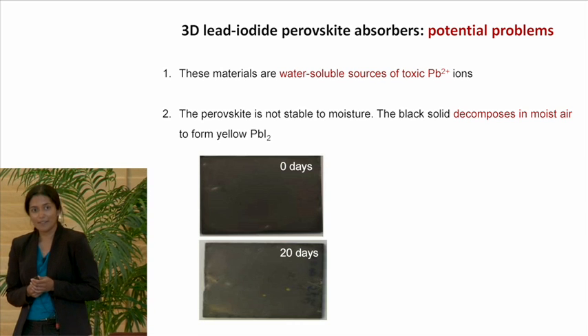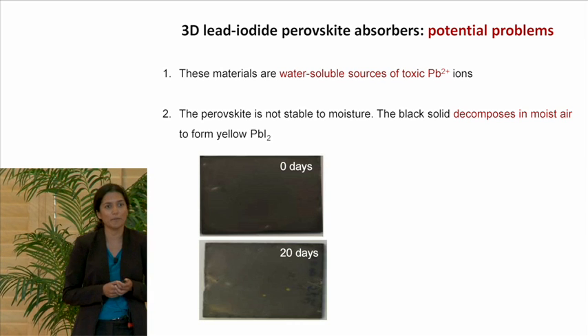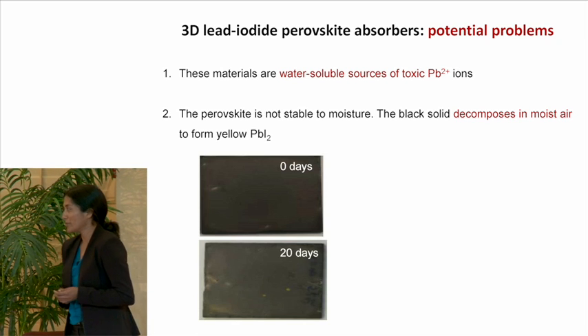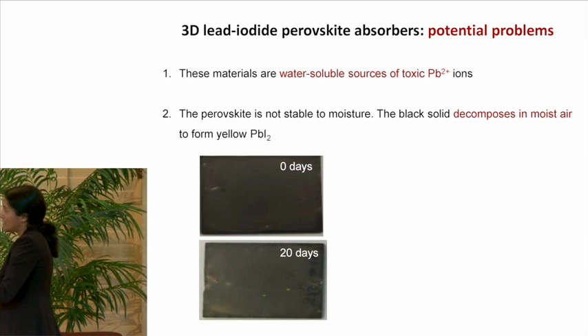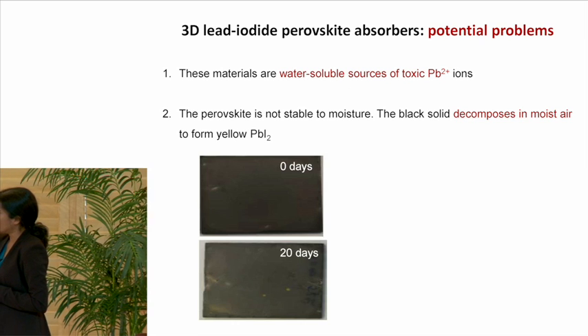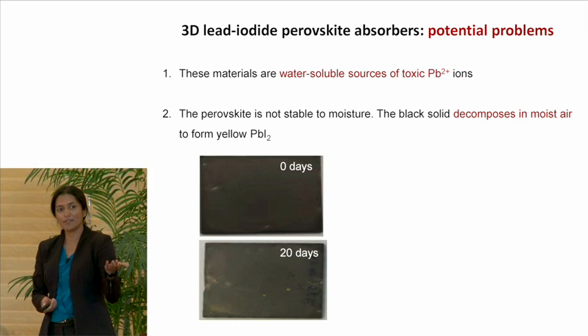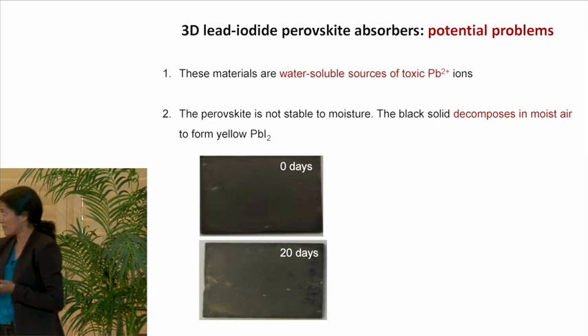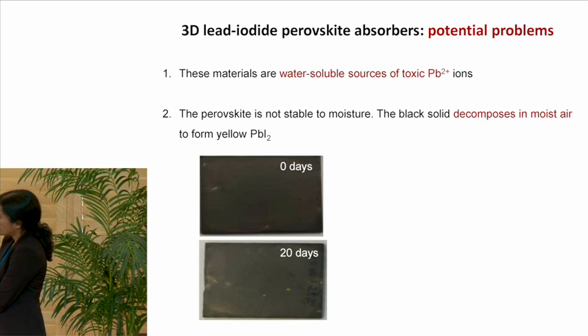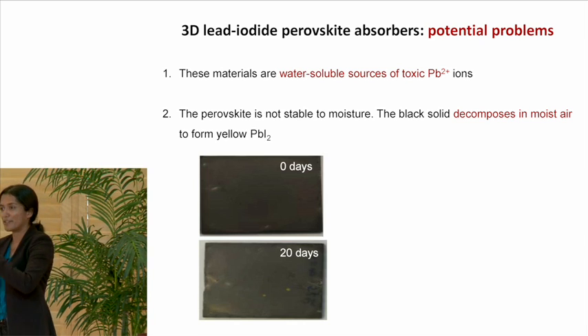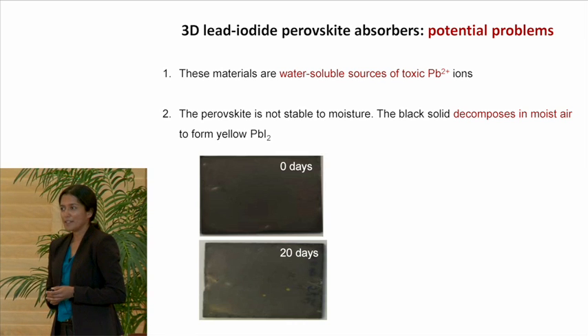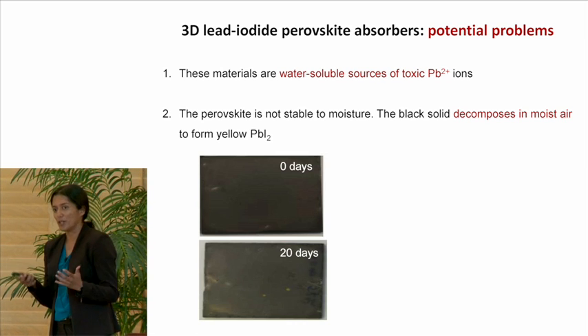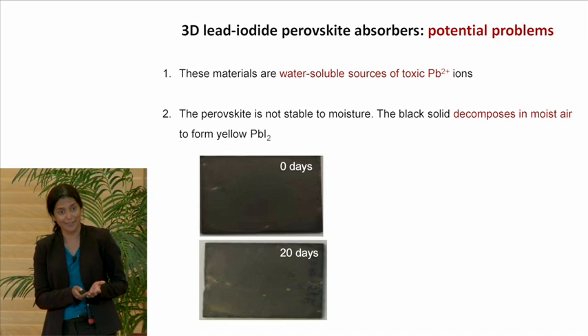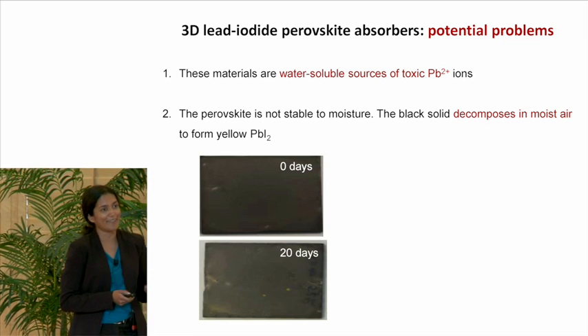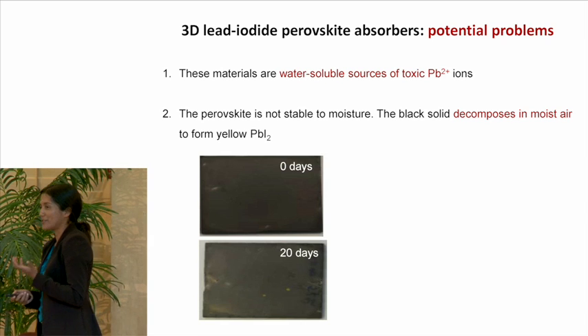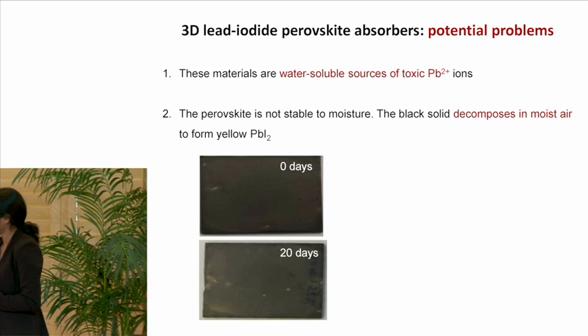Another problem that we have seen in our labs, we've seen this firsthand, is that these materials are not stable to moisture. So we can form nice uniform black films of this material, and here's a nice annealed film of the 3D perovskite, and if you just let it sit on a bench in the lab over the course of a few days, I hope you can see this, there are these yellow patches that start forming on the surface of your film. So it's bad news when your black solar cell absorber turns yellow. That means it's not absorbing sunlight. So these yellow patches are lead iodide patches that form. This material converts to lead iodide in ambient moisture.